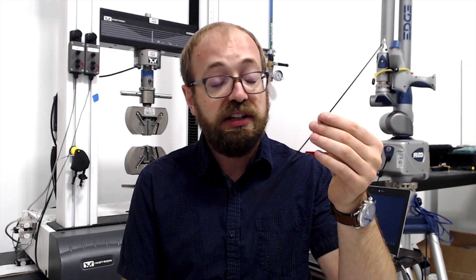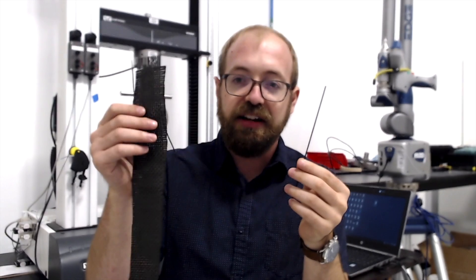That's because we're using a thermoplastic. We've devised the process for additive manufacturing whereby I can take this thermoplastic which doesn't cure, it just melts and freezes. Essentially I weld this thermoplastic as opposed to curing this thermoset. I can do all of this outside of an oven and without tooling or very minimal tooling.